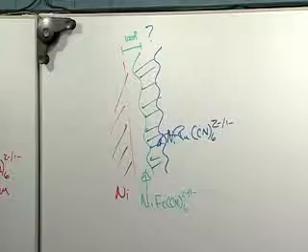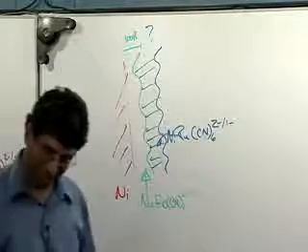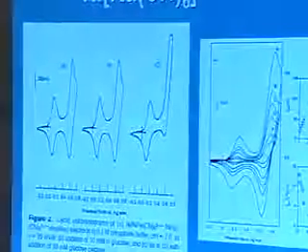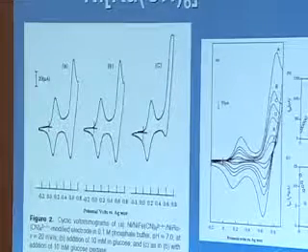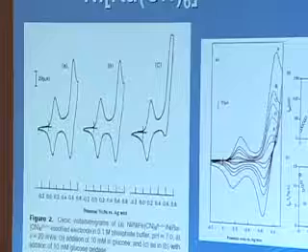The potentials are absolutely wrong for that. The iron 3 is not oxidizing enough to oxidize ruthenium. That's a positive delta G of almost half a volt, which will never happen if you believe that delta G means anything. So the irons are not strong enough oxidizing agents, based on the cyclic voltammogram, to do this. So even though we laid this layer down sequentially, this can't be the right picture.